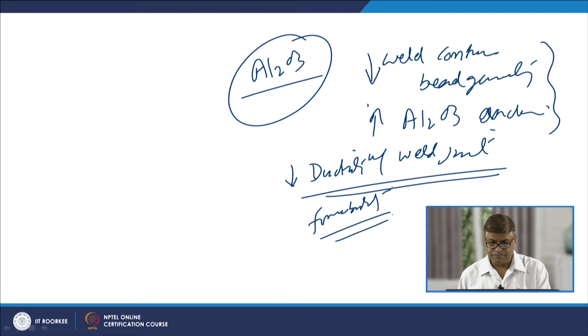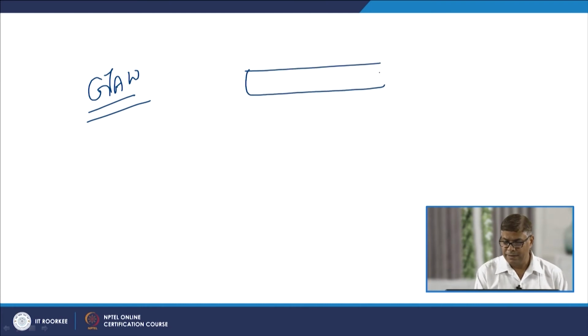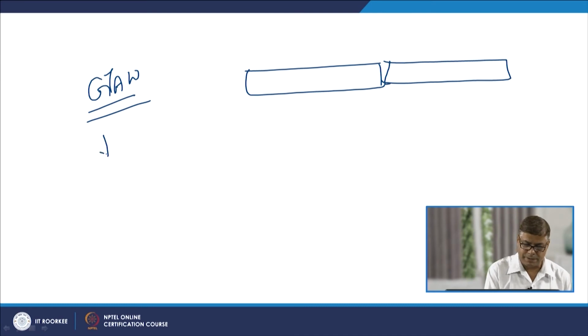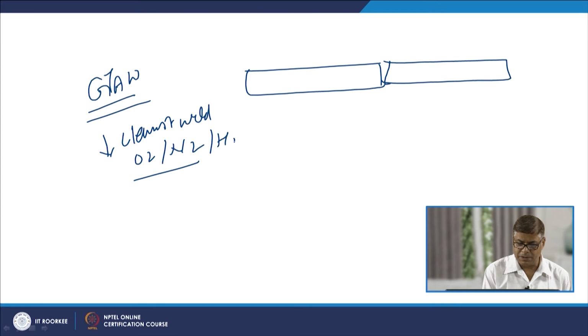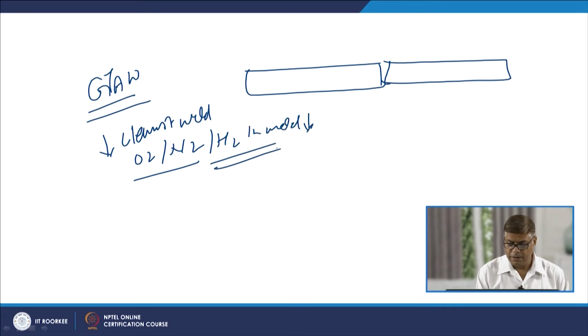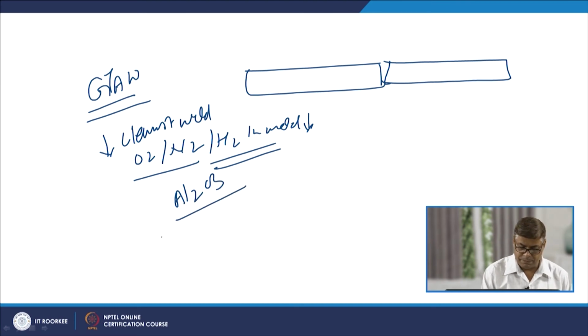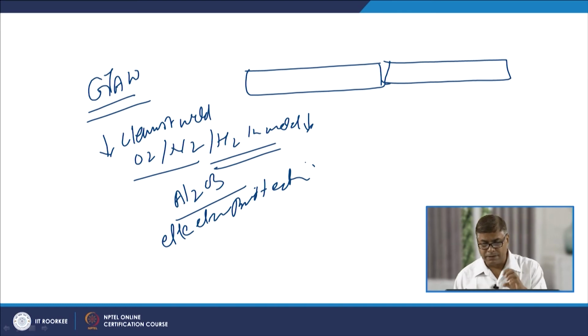On the other hand, when the gas tungsten arc welding process, GTAW, is used, since it is the process which offers the cleanest weld, the oxygen, nitrogen and hydrogen content in the weld metal is minimum. So, the chances for Al2O3 are very less because of the effective protection available with the GTAW process, because the shielding is very effective. Argon or helium is used as a shielding gas, the arc gap is very close, the arc is very stable, and that is why the entry of the atmospheric gases in the arc zone is very limited, and that is why it produces a very clean weld.